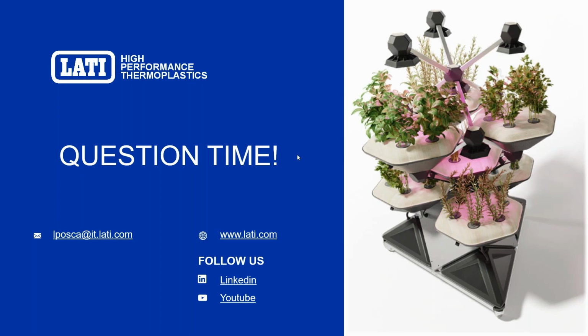How do you know or control the orientation of the filler particles? Very good question. Lati today can, not only Lati, I suppose, but from the year 2017, we have shown that we can simulate the particle orientation with a finite element injection molding simulator. We use Moldex 3D. And with Moldex 3D, you can actually see how the flakes will orient in the part. And then you can post-process these numbers into a thermal simulator, and you can actually describe the performance of the real part, not as an average part, but the real part.